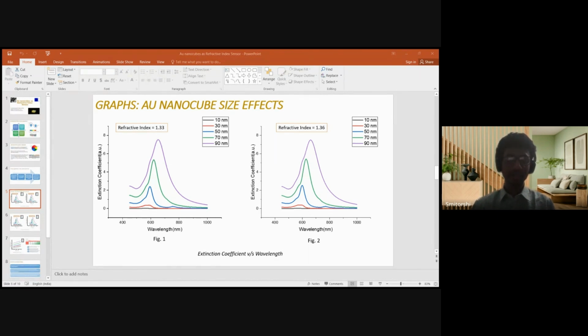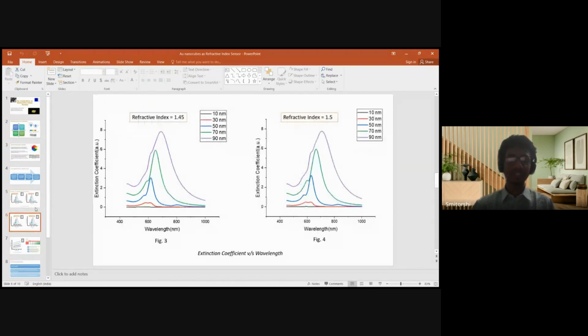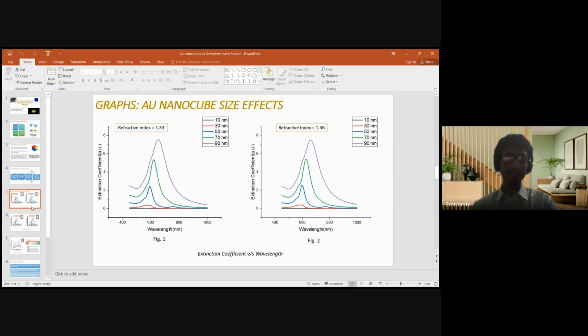We have observed that as the size of the nanocube increases, the shift in wavelength becomes much higher and much broader, whereas in lower sizes, the color shift in the nanocubes becomes much sharper and much smaller. Also, we have observed that as we change the refractive index, the changes are not that pronounced. Because of a medium change, the nanocubes aren't extensively affected, and it is giving steady rises that we observe in all four graphs.